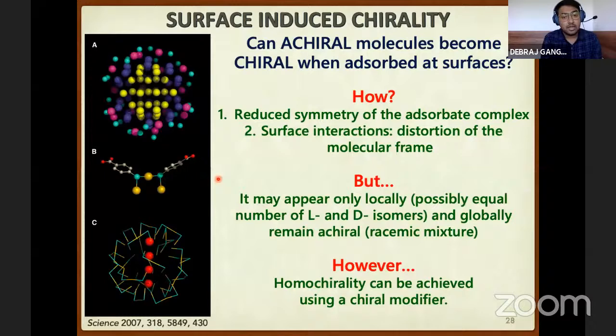Because when a molecule is adsorbed on a metal surface, the metal surface can induce two things in it. One is that it reduces the symmetry of the adsorbate complex, or the analyte metal adsorbate complex. The second thing is that there can be surface interactions, or distortion in the molecular frame. So these two things can distort the achiral molecule when it's on the metal surface, and they have observed that it may have some induced chirality. But this induction of chirality may be only local.